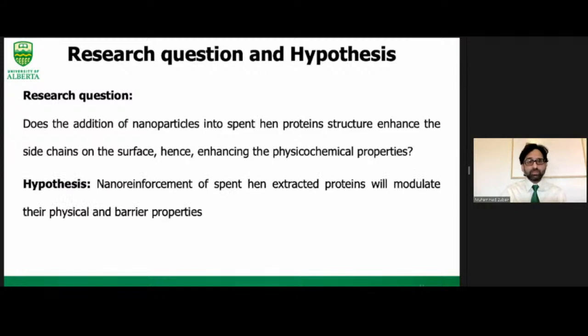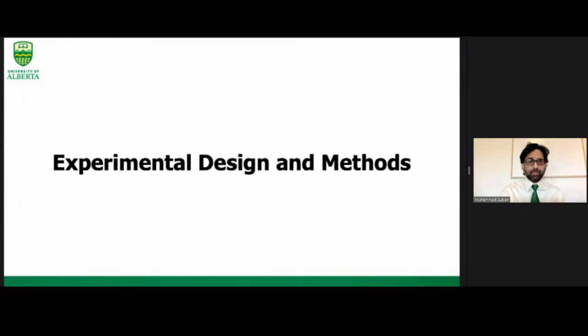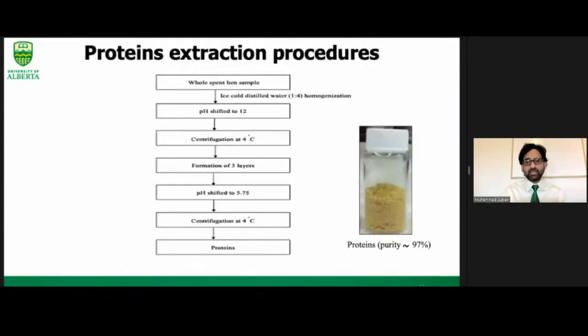Based on this research question, the hypothesis for the research project is that nano-reinforcement of the extracted spent hen proteins will modulate their physical and barrier properties through the addition of nanoparticles. Based on these, the following experiment design and methods were used. First of all, the proteins were extracted from the whole spent hen. Whole spent hen was mixed with water at a 1 to 4 ratio. Then the pH of this mixture was shifted to 12 using sodium hydroxide, and this was centrifuged. Furthermore, 3 layers are formed, and then the pH was shifted to 5.75, the isoelectric point, to isolate the proteins.